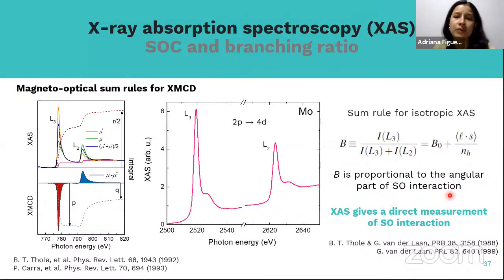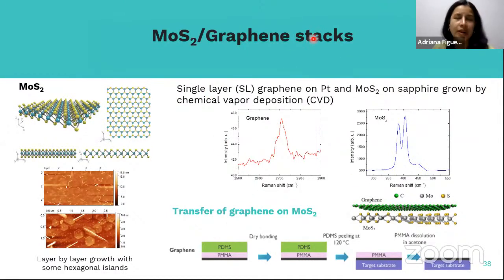So we took our samples. What are the samples that we took? We have graphene interfaced with MoS2. This is in collaboration with people at IMEC in Belgium, who grow graphene separately using chemical vapor deposition, and they also grow samples of MoS2 by chemical vapor deposition. Then they transfer one on top of the other using what they call a dry transfer method. We end up with a stack of MoS2 with graphene on top: single-layer MoS2 with single-layer graphene on top. These are images of this kind of stacks that we got, using AFM.